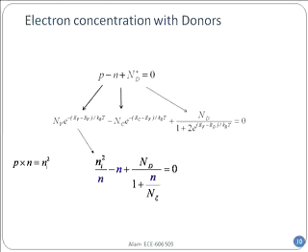Anytime you have a device, doped or undoped, but in equilibrium. You see, I haven't applied any voltage here, right? Doped or undoped in equilibrium, that one is always correct. P multiplied by N. And so you can see, in order to get the value of P, I can simply write Ni squared divided by N. No problem, right? Second one, well, N is N, no problem. And the third one I just derived.